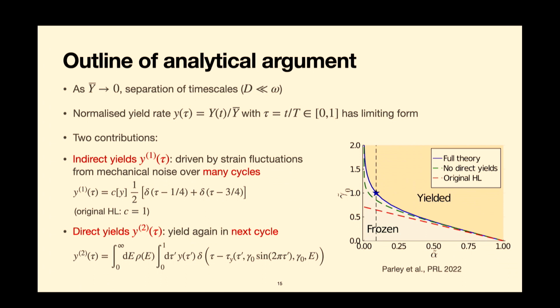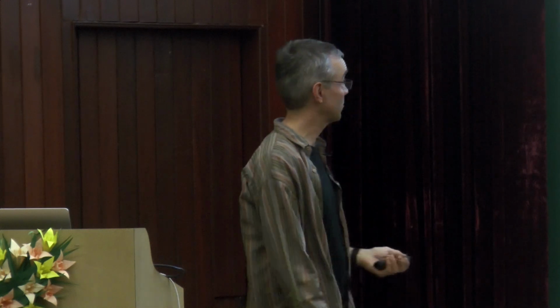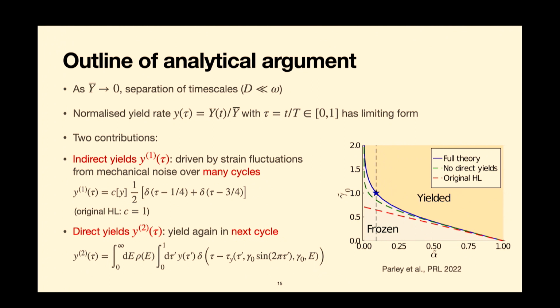And it turns out, and really the most important thing for me is to try and get across to you these things in red rather than the math necessarily. It turns out there are two types of yields that happen near this dynamical transition. One are the indirect yields, where you have a local element that over many cycles is basically just being moved back and forth. But occasionally something somewhere else in the material yields, and then this local strain gets a little perturbation, and then manages to cross its yield barrier. So that's what we call an indirect yield, because it's not directly caused by the perturbation, but it's caused by stress perturbations coming from elsewhere in the material. And the way we are parameterizing our strain, this happens only at the extremes of the deformation of the material, which makes sense, because that's where you have the highest chance of yielding if you're only getting small strain perturbations.